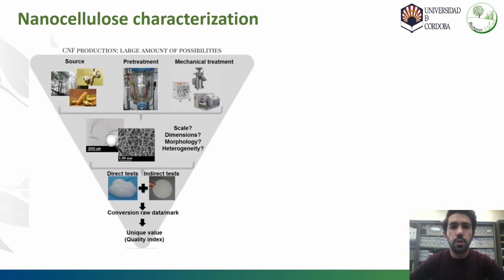As we have seen, there is a wide variety of possibilities when it comes to producing cellulose nanofibers. For example, for the shown raw material, there are a multitude of combinations of pretreatment and treatment to produce it. At present, there are at least 7 pretreatments and 9 mechanical treatments, which indicates that for the same raw material we can obtain 63 different nanofibers. So it's very important to follow standardized analysis and create a quality index to distinguish between the different samples and reflect information regarding the nanofibrillation and properties.